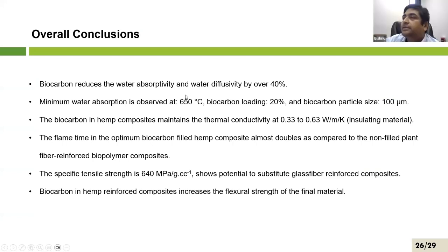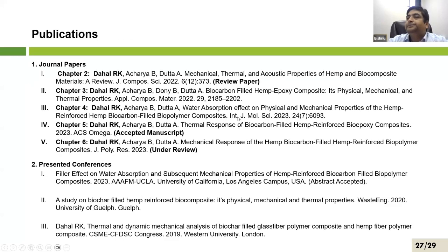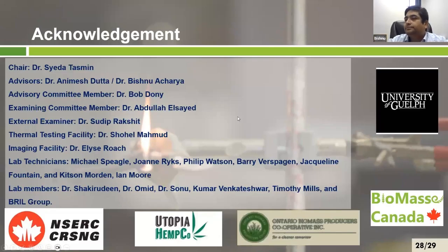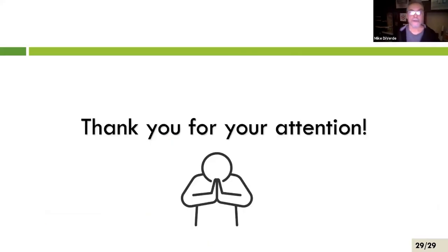Yeah, so we found that the optimum condition could be 650, 20% loading, 100 micrometer biochar size could be ideal for this kind of composite application. Very impressive. And your 20% loading, is that 20% of the weight of the entire face sheet? I want to make sure I understand that term. 20% of the total weight? Yeah, 20% of the total weight. Okay, so whatever it weighs, 20% is the biochar.